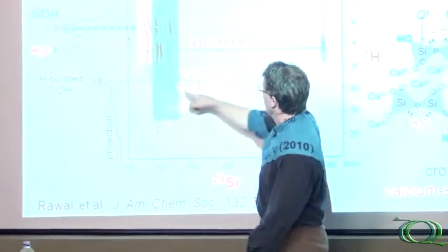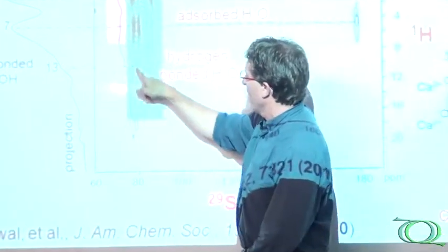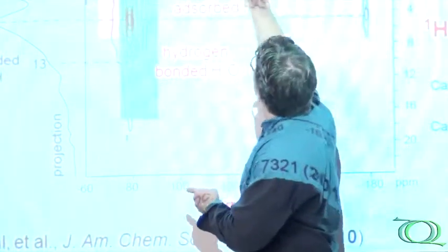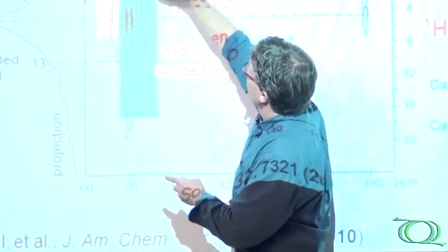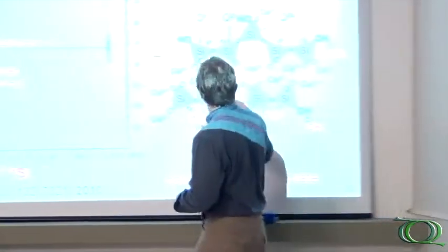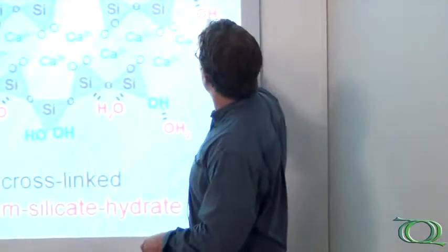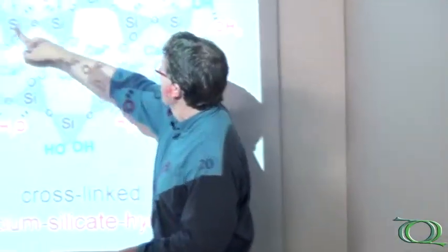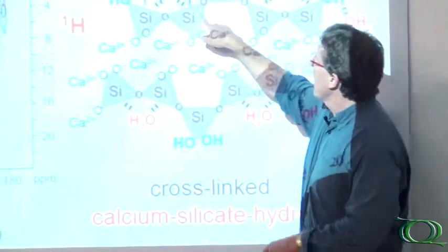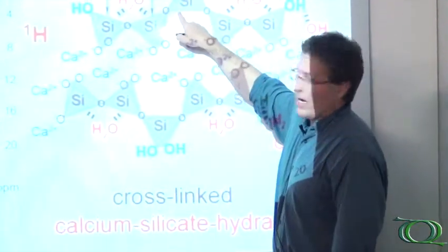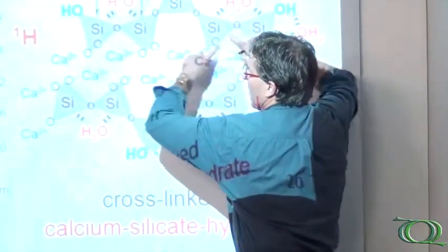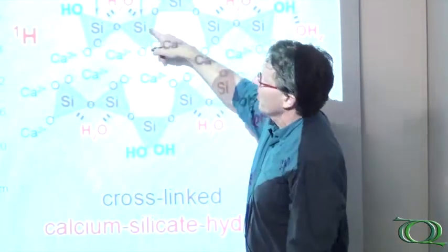Show a very high amount of interactions with water and with the silanol species. This adsorbed water being one, and then hydrogen bonded out here. So from the same type of method of the dipole coupled 2D experiments, one can establish that yes, these are strongly interacting with water, and then you can correlate it to the types of structure of these calcium silicate hydrates, which then form these cross-linked hydroxyl group species, which are the evidence of solidification. So this is what solidified cement results, it's these extended chains of cross-linked calcium silicate hydrates.